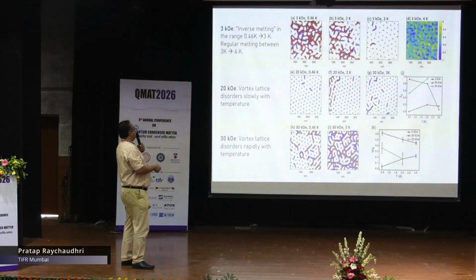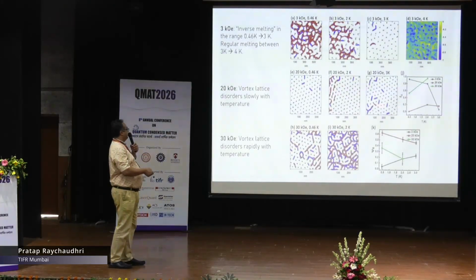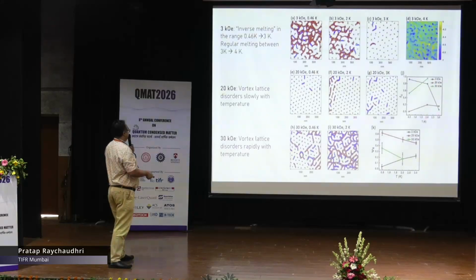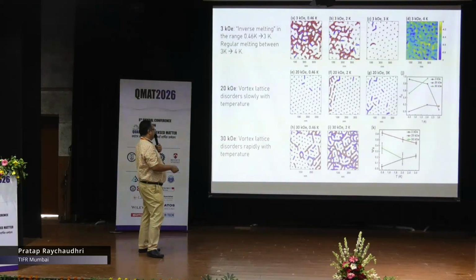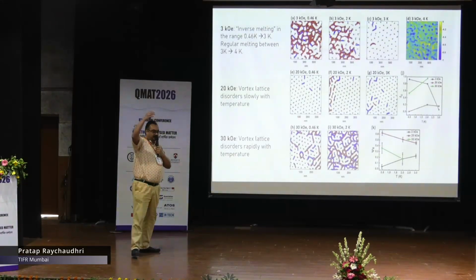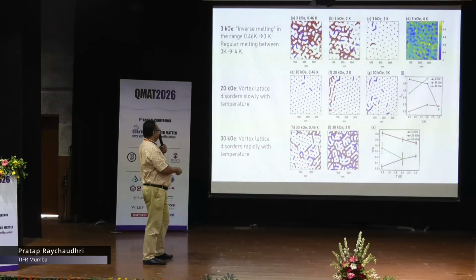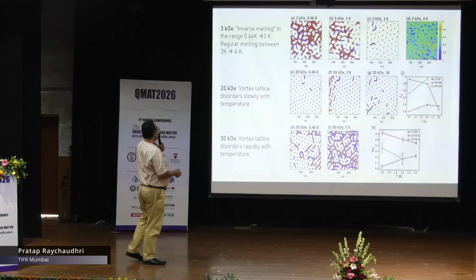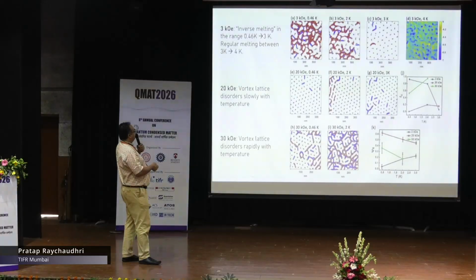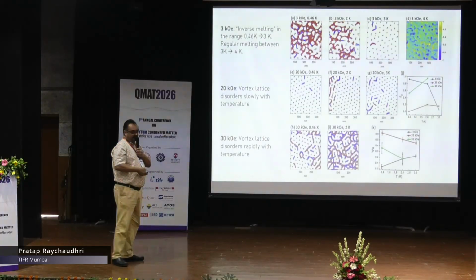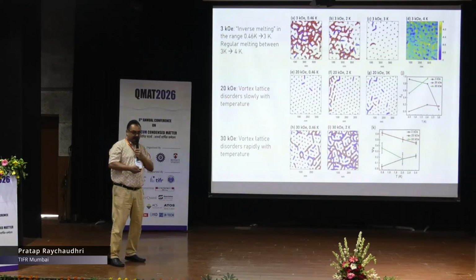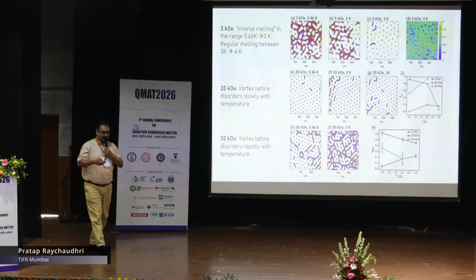At 20 kOe state, of course, nothing much happens over this temperature range, it remains ordered, and at 30 kOe state, you have just already the high field disordered state, the high field vortex liquid state, which becomes more mobile. But here what you have is completely counterintuitive, where increase of temperature has converted a liquid to a solid.